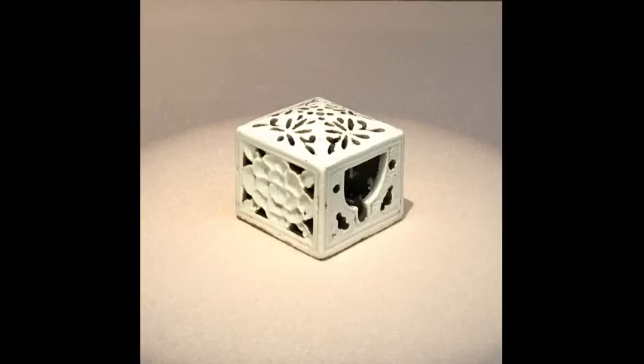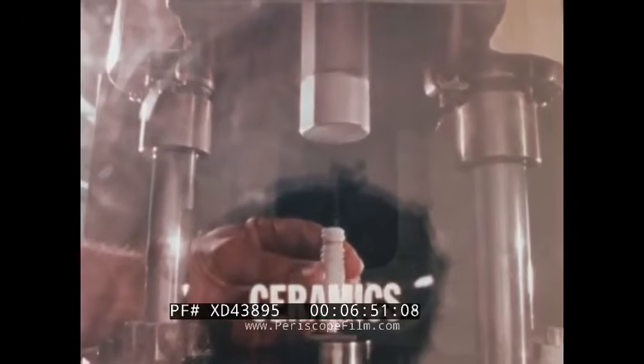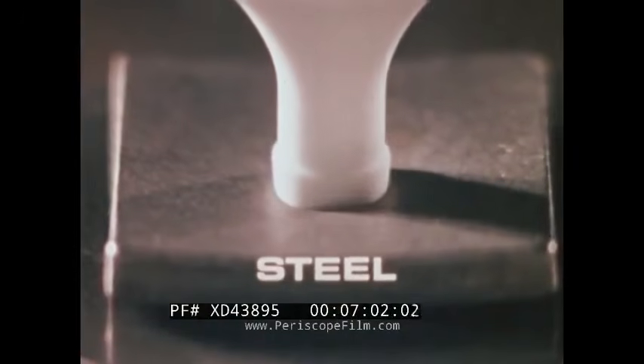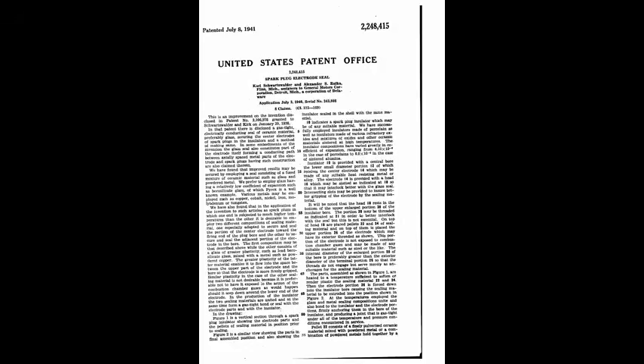General Motors researchers approached the problem by separating shaping from the traditional idea of plastic clay. The 1942 patent described mixtures dominated by alumina with controlled amounts of silica-bearing material and, when needed, small additions that helped sintering. Instead of depending on large quantities of clay, the powder could be mixed with a temporary organic binder, including thermosetting resin and a lubricant. The mixture was first pressed into a preliminary form. Then it was subjected to enormous pressure in a mold, on the order of tens of thousands of pounds per square inch. The pressure packed the particles closely enough to create a fragile green body. It looked solid, but it had not yet become ceramic. The binder held it together only long enough for the firing operation.